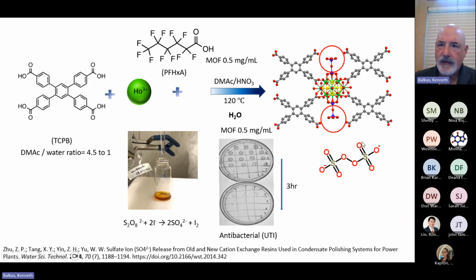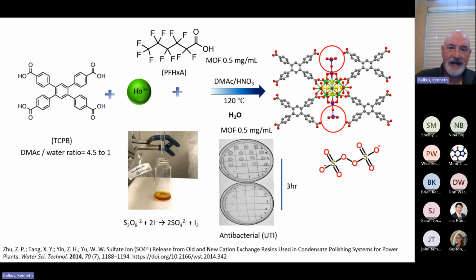This is actually kind of an interesting story because, again, you get a crystal structure and you say, where did this come from? Because when the student brought me the structure, she said, well, I have a persulfate bridge in this structure. And I'm like, where did that come from? And it turns out there's sulfate in their DI water. Obviously, I said, you use tap water? She said, no, I use DI water. And of course, you take the DI water and run it on the ICP, and you see the sulfur in there. What happens is some of these ion exchange resins, when they start to break down, the pH changes. You get some of these other species that show up in your water, and they can actually end up in some of these structures.